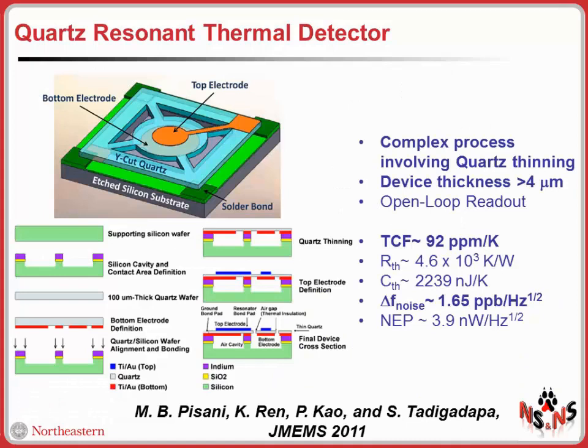And this idea was experimentally demonstrated a few years ago by Srinivas Tadigadapa's group at Penn State. They showed that by micromachining a quartz substrate, it's possible to build resonators with a device thickness in the order of a few microns that have very large temperature sensitivity. They are very well isolated from the heat sink. You see 4.6 10 to the 3 Kelvin per watt, so they're very well isolated. Small thermal capacitance, and of course, they still have excellent noise performance due to the very good quality factor of quartz resonators. In fact, they demonstrated noise equivalent power in the order of 3.9 nanowatts per square root of Hertz.